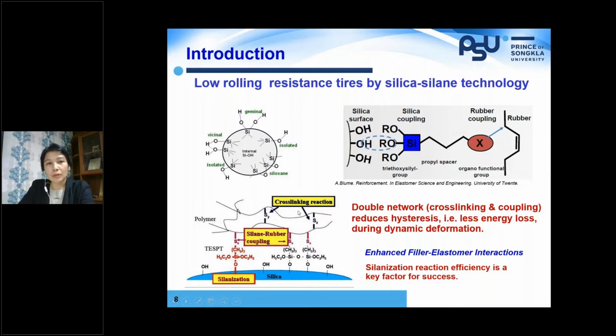So the principle of the low rolling resistance tire that we obtain from this silica-silane can be simply described by the effect of a double network, because once we do vulcanization, we have cross-links. So we have chemical cross-linking, and we do the coupling reaction. So you also have a covalent bond between filler and rubber, and this double network leads to lower hysteresis. That means we have less energy loss during dynamic deformation. And the silanization reaction efficiency is a key factor to success. So we are talking about two different steps that we need to look at carefully when we use silica-silane in rubber compounds: the silanization during mixing and the coupling during vulcanization.